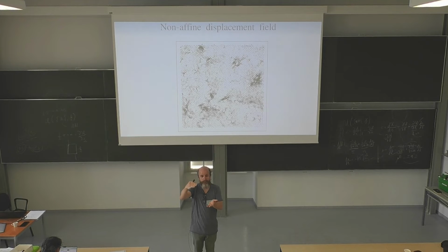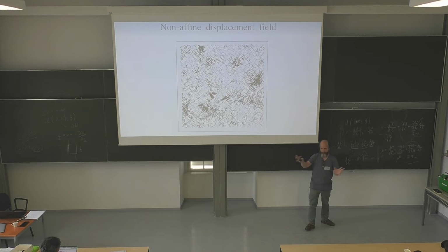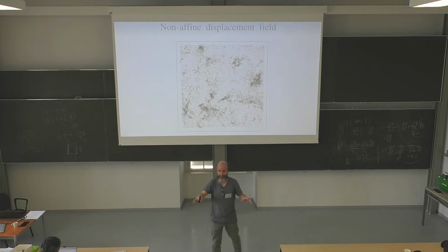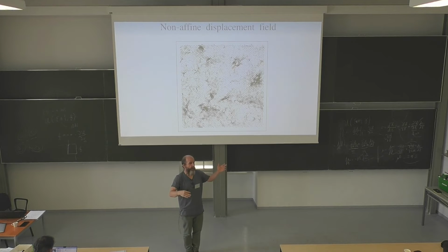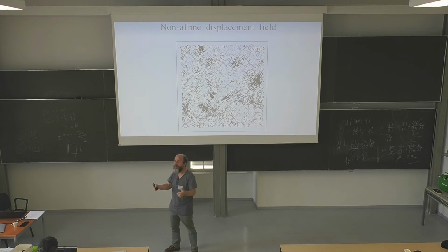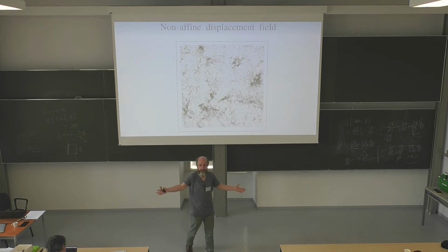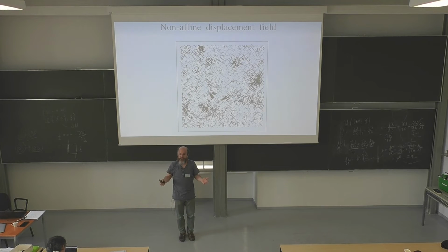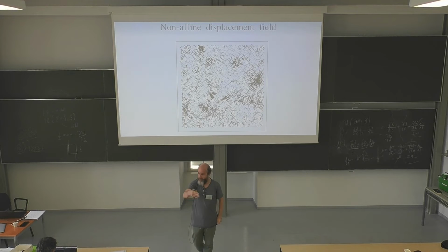The elastic response is reversible, as I said, totally reversible. So you can shear back, so long as you are along an elastic branch, it's completely reversible. So here I simplified a lot the calculation by looking at a single strain, bypassing some details about how you change variables. The point is that this formalism exists. The linear response of solids can be entirely calculated. It's just a second derivative, right? It's nothing else. It can be entirely calculated, and it means that in practice, when you do numerical simulations, if you have an inherent state, if you have any configuration, you can calculate any modulus just analytically, okay?